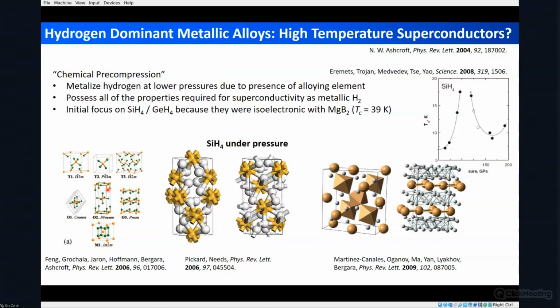And the first system that he looked at was silane, and he said that potentially adding silicon to hydrogen could induce chemical precompression. So what that means is that the silicon addition would actually increase the density of hydrogen compared to what you would have without silicon, and the resulting system would have all of the desired properties for high temperature superconductivity.